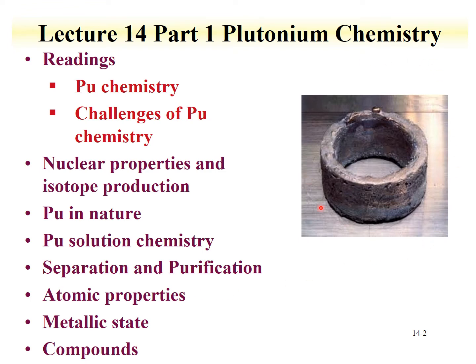And here we see an example of a ring of plutonium. This is made from an electrochemical process where you can form plutonium in a molten salt. The melting point of plutonium for a metal is relatively low. It can drip off the electrodes and form into rings, and there's a reason that they would form this plutonium into rings, and it has to do with criticality safety.